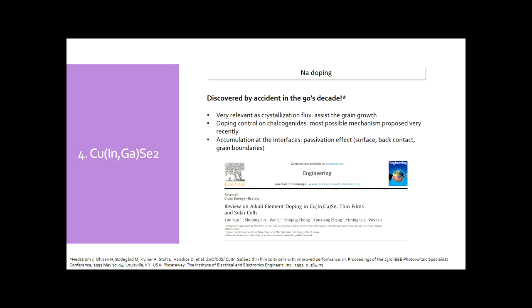And after these generalities of this technology, normally this material exhibits three efficiency jumps in its history. The first one was thanks to the sodium doping. The second one was the discovery of the gallium alloying for graded band gap, and then the third one, the alkali PDT with heavy alkalis. So sodium doping, this is a very nice example of an accident in a lab because someone changed the typical borosilicate glass that was used at that time in CIGS for a cheaper soda lime glass.